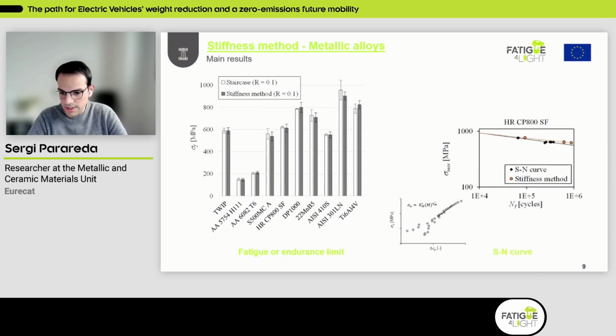And also the good point is that, as I mentioned, we can get this extra information from the material, from this fatigue damage evolution. And we can process all of these data and also obtain a first approach of the SN curves. So here on the right-hand side, you can see the SN curve obtained following the ISO standard, and then the results for the stiffness method. So it's clear that maybe we have some slight deviations, but the main idea is to obtain further results in terms of the fatigue limit and also the SN curve in about 2 hours.